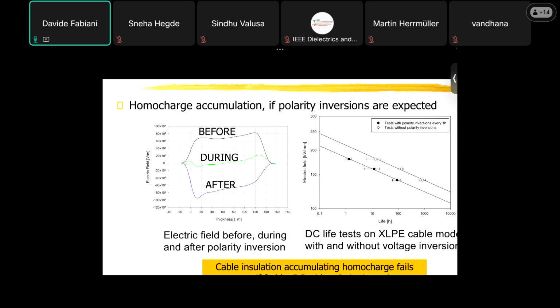If you accumulate homocharge, the electric field before polarity inversion, as you can see here where there is homocharge accumulation, is lower than what happens in the middle, okay? And this could be the applied field, the average field, and you can see that the field here is lower. Then you apply a polarity reversal, which is sometimes requested to invert the power flow in your cable. The problem is that what was homocharge becomes heterocharge once you have reversed the polarity of your electrodes. And what you can see here is that after polarity reversal, the electric field in correspondence of this electrode becomes very high. And this can create, of course, an extra stress to your